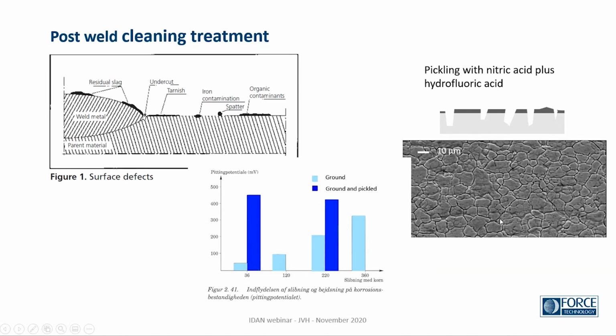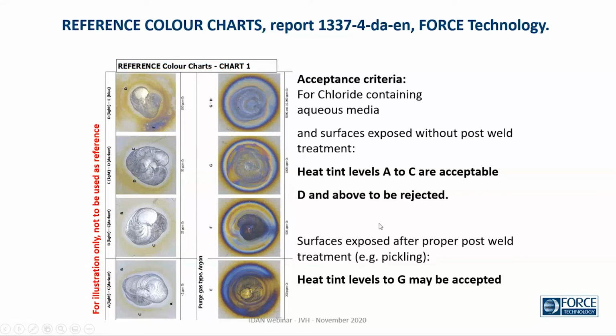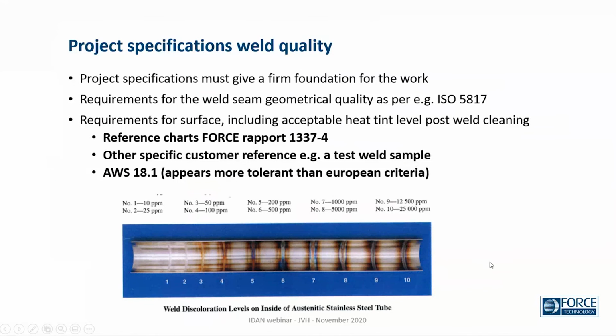Just to mention that the references that we provide have also given an American standard. We were first, I could say, but some years later, the American Welding Society made a standard called 18.1 with reference pictures like this, where you could define that you want your welds to be at level 3 or better. It appears that they are a little darker, but you have to be aware that the printer you use, or the monitor that you look on, would be slightly different. So in fact, the sample might be a little less red than this one in the actual world.